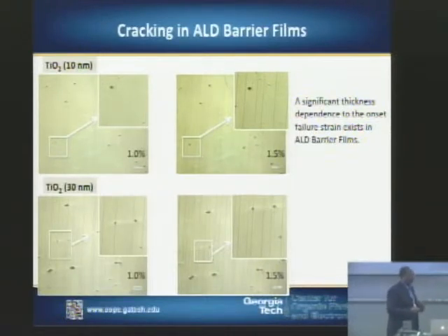So from a manufacturing point of view, you want to make this as thin as possible, but it's still not clear what it does to the mechanical properties. So if we look at a 10 nanometer thick film, you can see if I strain this now in tension to 1% strain, I don't detect any cracks in the film. If I go to 1.5% strain, you see the parallel cracks that actually form here.